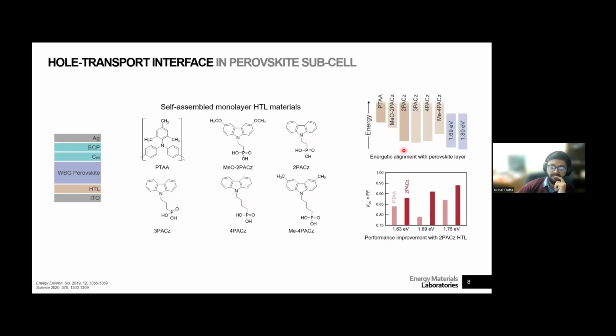The first thing we looked at was the energetic alignment. You can look at the HOMO levels of these materials here, and this is the band diagram of the 1.69 eV perovskite, which is suitable for silicon tandems, and the other one, 1.80 eV, which is suitable for perovskite tandems. You can already see that these three, for example, align much better than the other ones. We attempted to work with these materials, but the fourth was difficult to dissolve, so it didn't really give us very good cells. For the third, the yield was a bit lower, but the performance was comparable. But because the second had the benefit of both the yield and the performance, I decided to go with it.